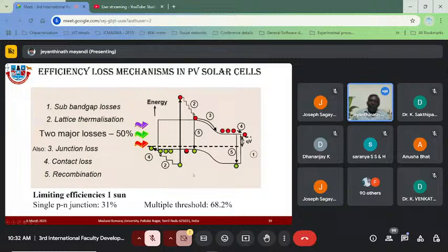Sub-bandgap losses. So as when a photon comes in, you see this limitation here in the band gap, and then the lattice thermalizations, and the other losses are minor, which could be junction losses, contact losses and recombinations. The recombinations can be removed when you have high quality, non-impure material, then you can remove these recombinations, and you have a contact. If you could reduce the contact resistance, then that could also increase the transportation.